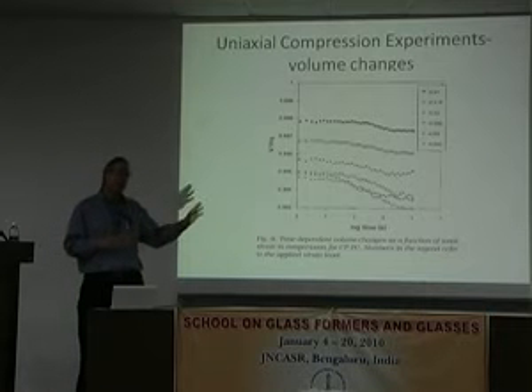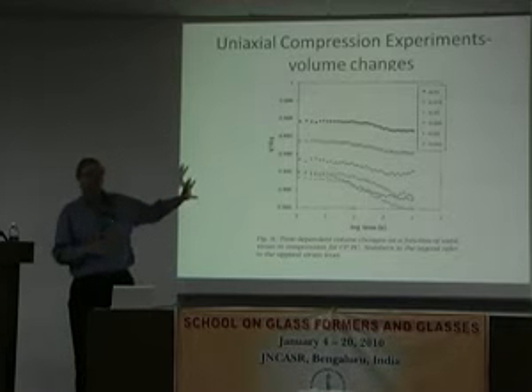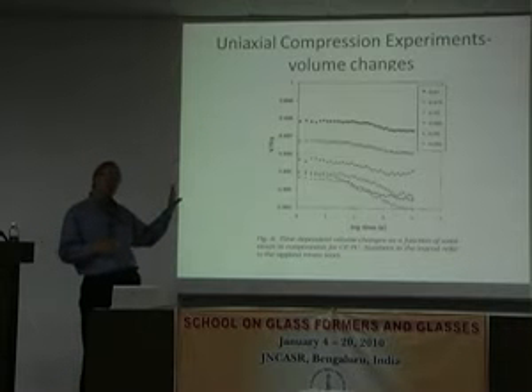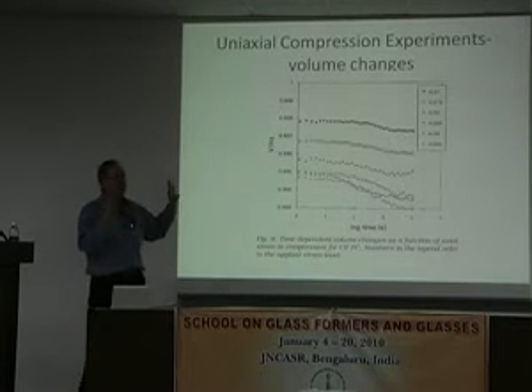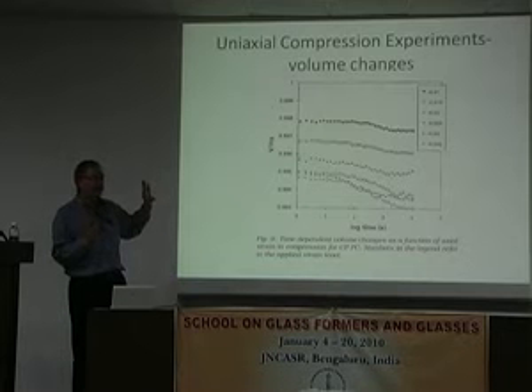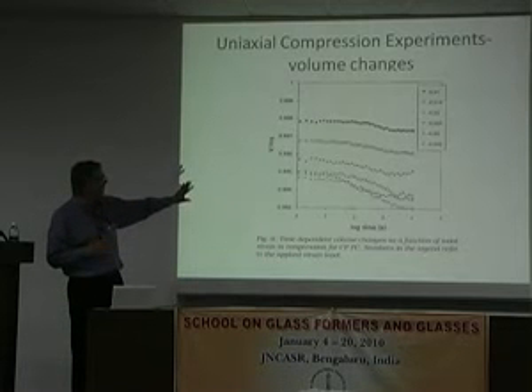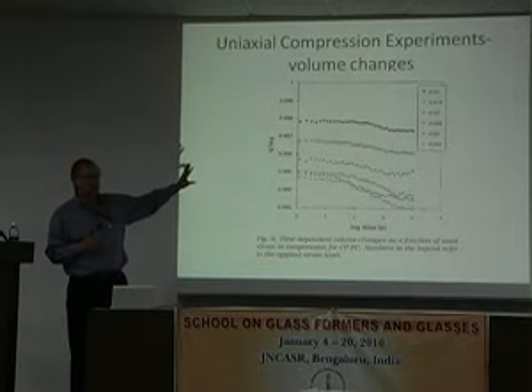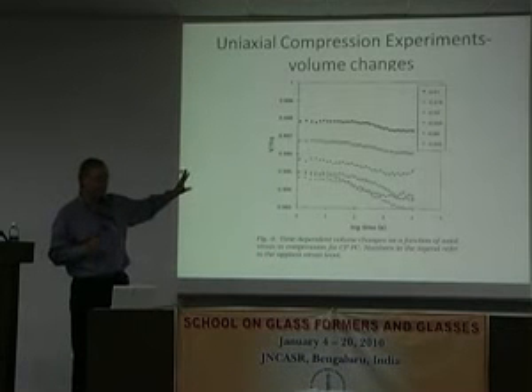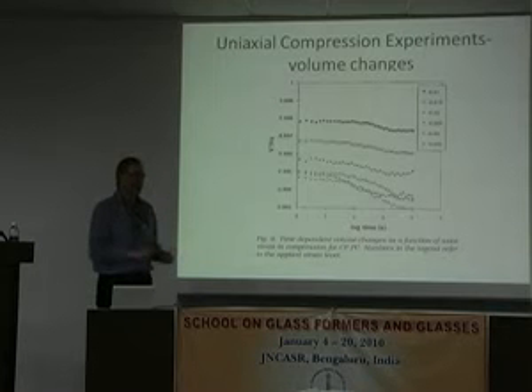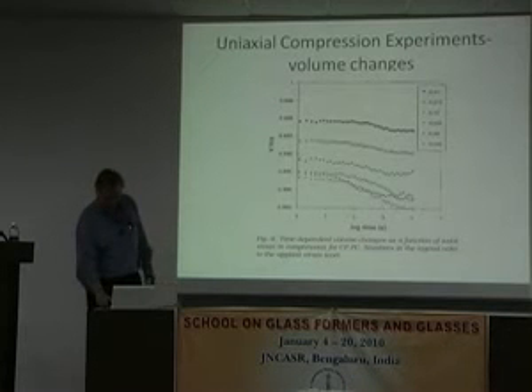So now this really does seem to imply that when I'm far below Tg and the stresses are higher, when I'm up by Tg, the moduli aren't so high, the stresses aren't so high. Here, the stresses are getting much higher, and they apparently are beginning to show signs of actually doing something to the structure of the glass, unlike my original anti-rejuvenation argument, right? So, in fact, Sandy Sternstein might be right.